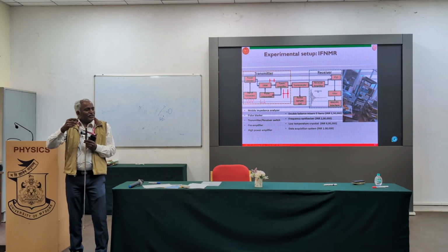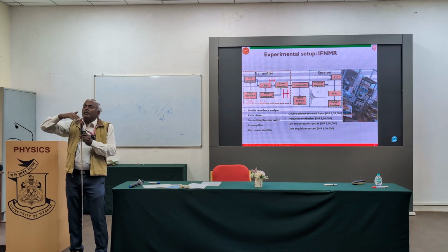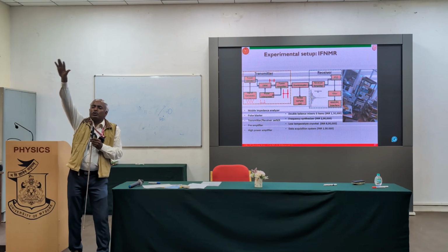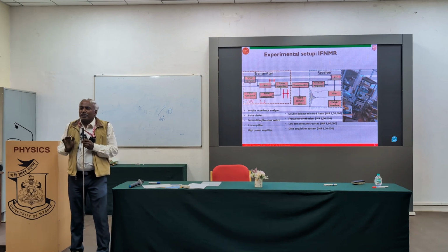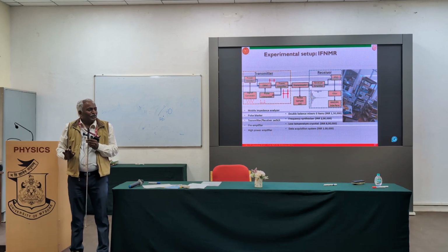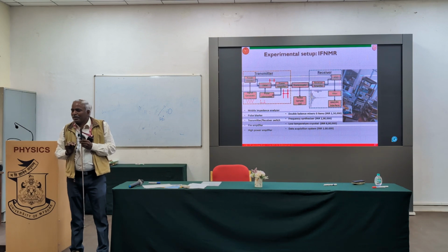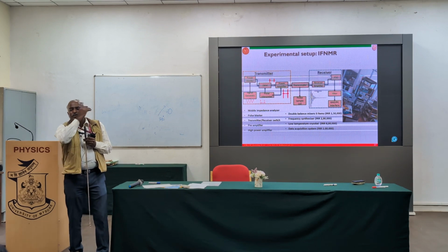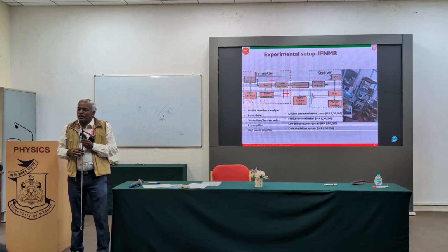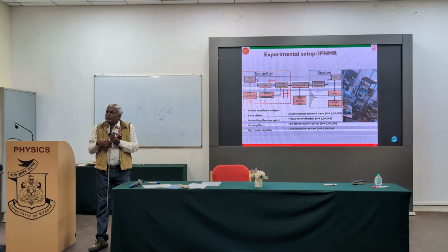At room temperature, the difference is so small. Just to tell you, whenever I showed the 2 energy levels, if 2,000 people are sitting on the ground floor, the ground state, only 1,999 people are sitting in the excited state. Only one person is causing the NMR signal to be detected. It is an extremely insensitive technique. That's why many people don't work with it. For that purpose, we went for low temperature. Whenever I do that, I can increase the difference, minimum 5 times, even 10 times. Like that, there are many other challenges associated with it.